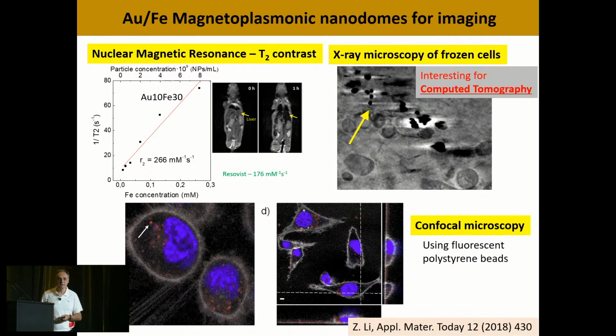And then another thing we did is to change our polystyrene beads to fluorescent polystyrene beads. And then we used a confocal optical microscope to see if we could see the particles. And indeed, you can see the red dots inside the cell. These are our nanodomes inside the cells. And with the confocal microscope, we can do slices, and then we can project them. And you can see here that indeed the nanoparticles were inside the cells when we do the projection of the confocal imaging.